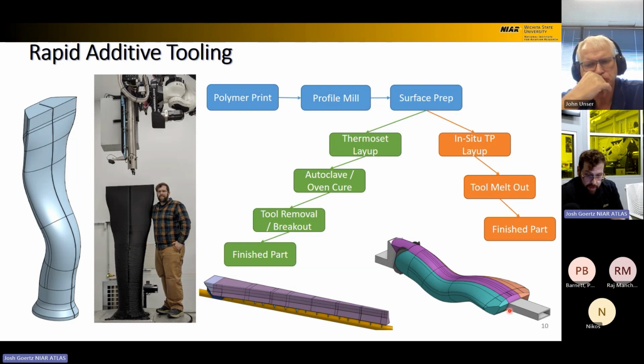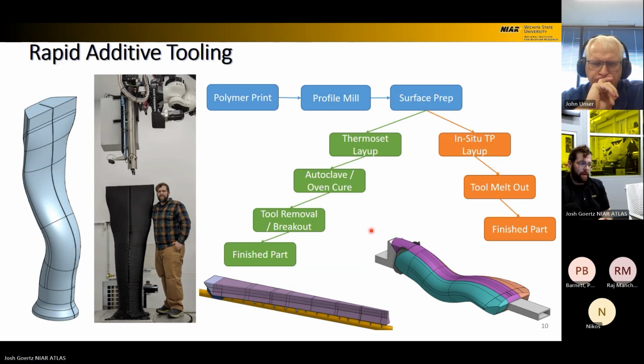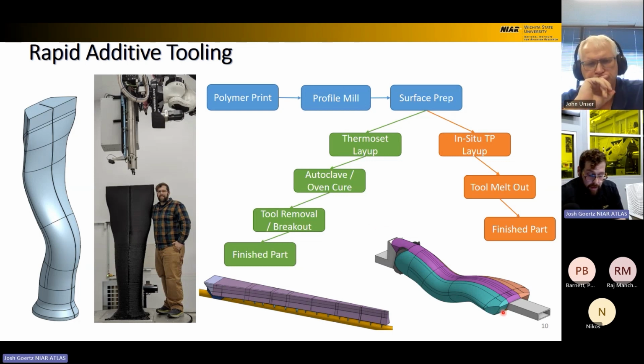The example tool designed on the right here is the same geometry as the rear portion of this serpentine duct that's on the left, but done in such a way as to put it on a rigid steel core, and that is to interface with a standard AFP machine horizontal rotator for doing higher rate AFP manufacturing compared to the single lane AFP manufacturing that we can do with the scram machine. In this instance, this would also be a melt out tool with this 4-segment serpentine duct.